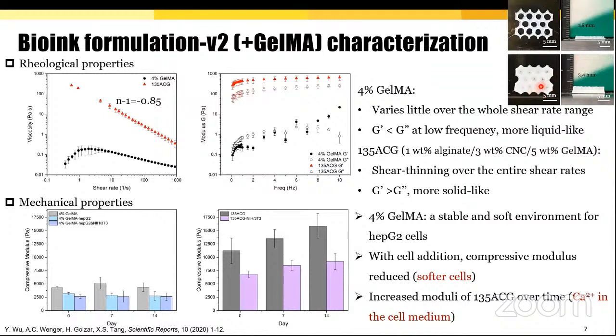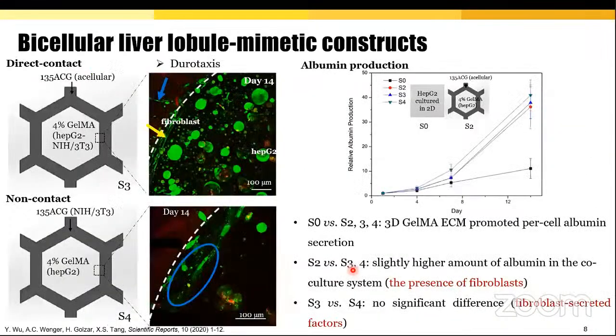collapsing occurred later. As mentioned previously, mechanical strength and the degradation profile are essential in developing bioinks, thus we did some tests on it. The compressive modulus of 4% GelMA hydrogels was around 4 kPa, within the range of the stiffness of a healthy liver, meaning 4% GelMA provides a soft and stable environment for HepG2 cells. Compared to the GelMA hydrogel, the hybrid hydrogels were much stiffer, over 10 kPa. Upon cell suspension in both bioinks, the modulus reduced due to the softer cells and the material voids. Interestingly, the compressive modulus of both acellular and cellular 135 ACG hydrogels increased on day 14, which can be attributed to the strengthening of alginate network by calcium ions in the cell medium.